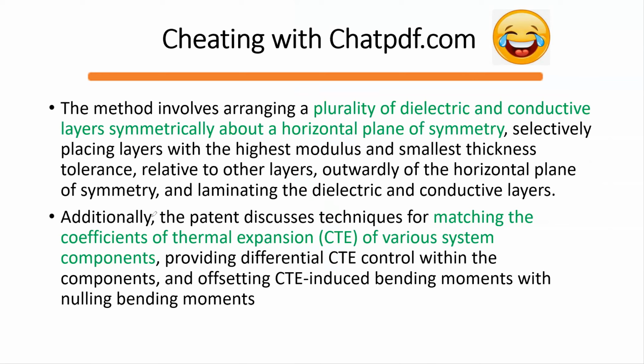It says that the method involves arranging a dielectric and conductor layer symmetrically above a horizontal plane of symmetry so that overall it could have a force balance to reduce the warpage effect. And then in matching the thermal expansion, the CTE, coefficient of thermal expansion, of various systems. Of course, you want to expand your IP, your patent, as broad as possible. So you do something to address the thermal expansion coefficient issue. So this is what this IP was about.